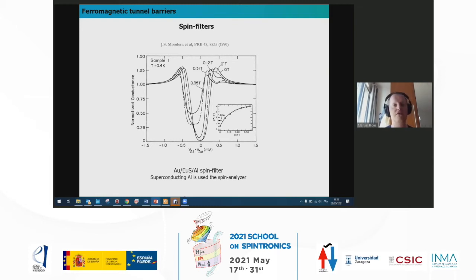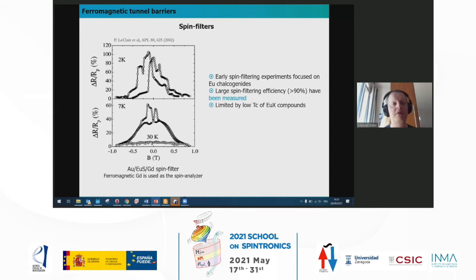I don't want to go into detail, but a few years later, well, actually 12 years later, this paper reported the first, let's say, TMR-like evidence for spin filtering. And there the junction was made of europium sulfide, that was the ferromagnetic insulator, and the ferromagnetic metal was gadolinium, and then there was gold on the other side. So you see the TMR was quite high, with a funny shape, but more than 100% of TMR.